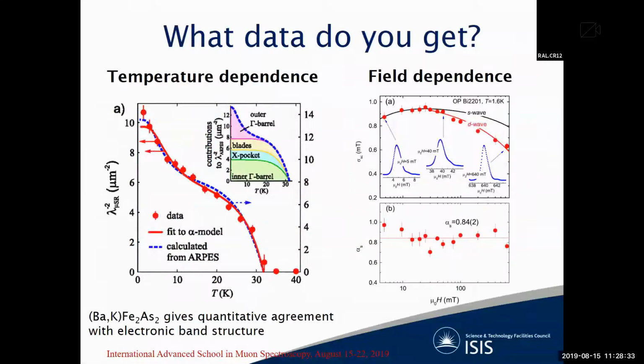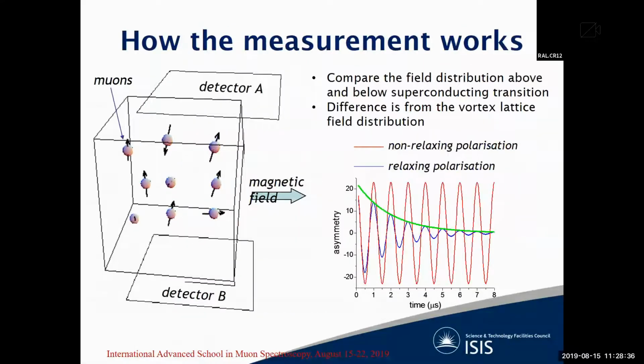Questions for Pabby? So I have a quick question. Is there anything you can really extract out of the field shift? Because when you do these measurements, normally you get a value from the mean magnetic field in the mixed state, right? Yes, you can normally see it in the measurement, you get the field shift, so you can track both. From this signal, you can track both the decay, the relaxation rate, and also the internal magnetic field. And normally in a superconductor, you should see this field shift below the transition.